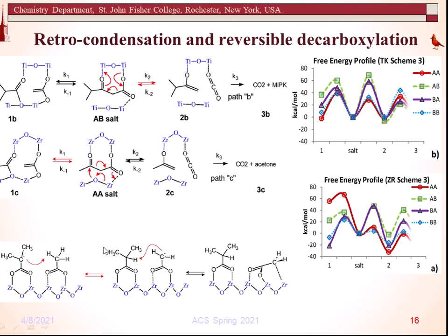The enolate is a strong base which may deprotonate the neighboring carboxylate, converting that carboxylate into the enolate. As a result, their roles are switched, and those pairs may engage in the process of stealing the proton from each other several times before the condensation step can take place. Such variation increases the entropy, so that the free energy goes down for those unsymmetrical pairs.